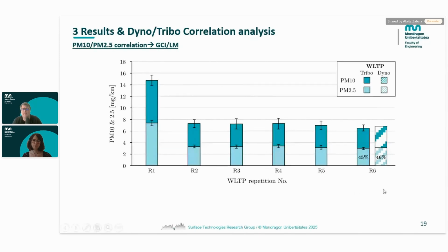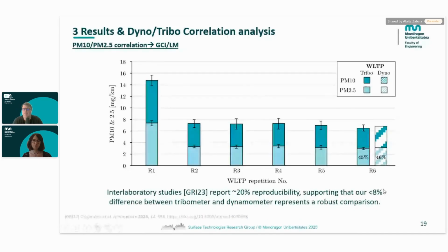between these tribometers. If we go to the literature, we can see interlaboratory round-robin reports that say that a difference of 20% between laboratories that comply with the GTR is quite normal. Because we obtain less than 8%, we can say that for this tribometer we obtain a really robust comparison. But what happens with other materials? We can see in the next slide.